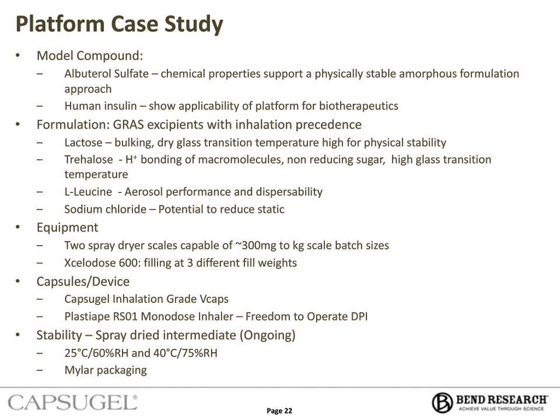roadmap for biotherapeutics. The formulation excipients we selected were GRAS excipients, so lactose as a bulking agent with a high dry glass transition temperature, and trehalose in the case of the insulin to provide hydrogen bonding as it's a non-reducing sugar. Leucine, as we talked about, for aerosol performance and dispersibility, and sodium chloride has the potential to reduce the electrostatic effect of these very high surface area particles.